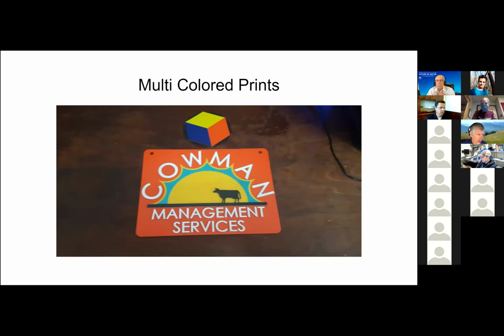We then tried multicolored printing. Our first attempts were unsuccessful because the different colors that we had available were of unlike materials and they wouldn't adhere to each other. While it turned out pretty cool, it was very labor intensive. We tried to allow 2 to 3 layers for each color and then calculate the time required to perform the task, pause the print, then change the color and restart the print. We also found that it is incredibly important when designing to be mindful as to which colors are applied over others. For example, the blue or black filaments are too dark of a color to be printed first because it tends to show through red, yellow, or white. We could print them first, but there would have to be more layers of the lighter colors so the previous shade wouldn't show through.